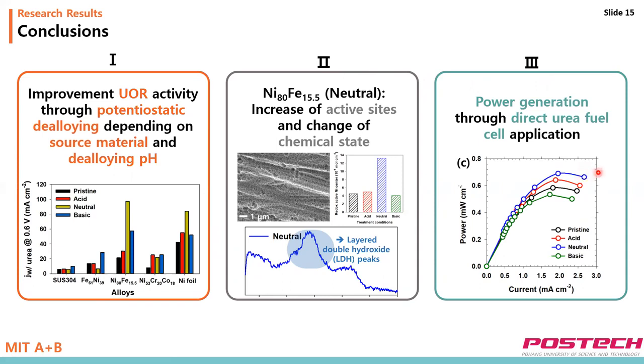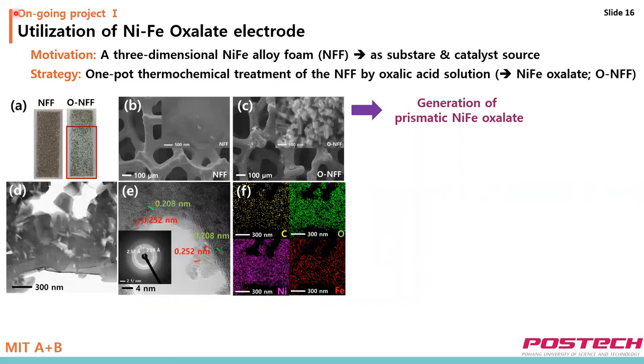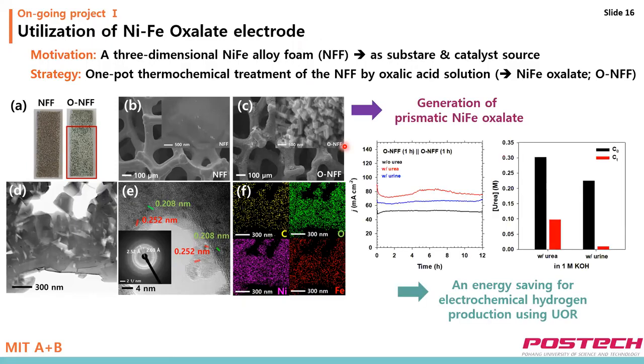Based on this result, my ongoing project is utilization of nickel iron oxalate electrodes. This project utilized a three-dimensional nickel iron alloy foam, both as a substrate and catalyst source, to create a self-supporting, highly efficient UOR electrocatalyst. So, one-pot thermochemical treatment of the nickel iron foam by oxalic acid solution generated prismatic nickel iron oxalate. These electrocatalysts exhibit excellent UOR activity that promises energy-saving hydrogen production.